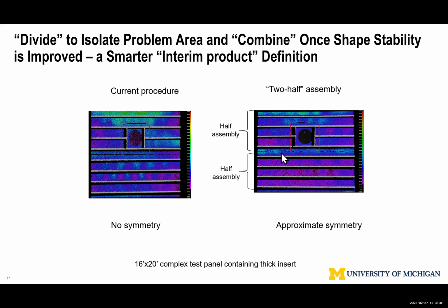That means don't weld this weld first. First deal with the two halves. Bottom half symmetry, top half you require special tooling. You're gonna weld thousands of those, right? And then that gave you the volume, the repetitiveness to build your knowledge, your expertise. And then you come back, tack stiffener, gave you the stability, finish tacking, and then once both sides get welded with the stiffener attached, and then you weld this weld.